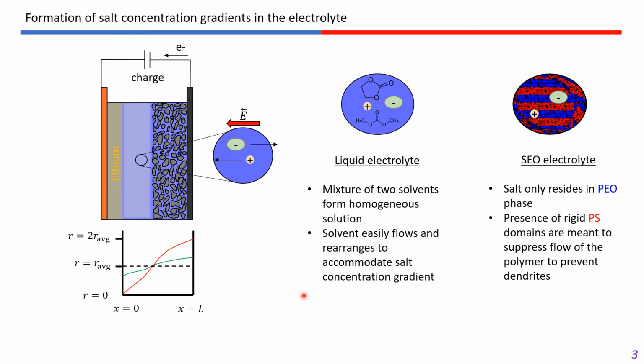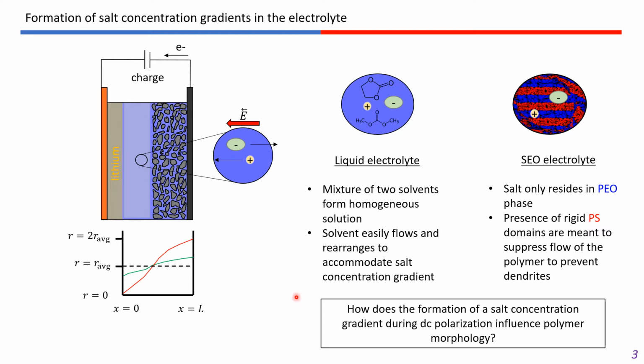However, in a block copolymer electrolyte where salt only resides in the PEO phase, it is not clear how the presence of rigid polystyrene domains might affect this rearrangement. In particular, the rigidity of these domains is meant to suppress the flow of the polymer to prevent dendrites. And so the question we want to answer is how the formation of salt concentration gradients during polarization influences the morphology and flow of the polymer.